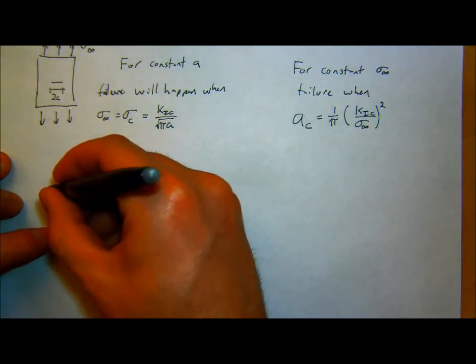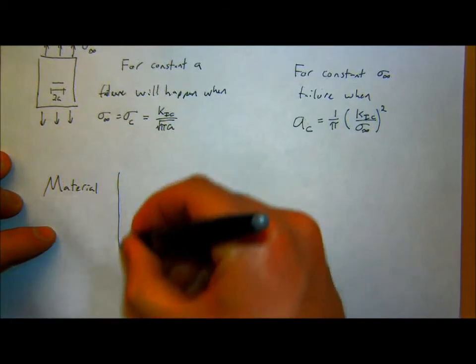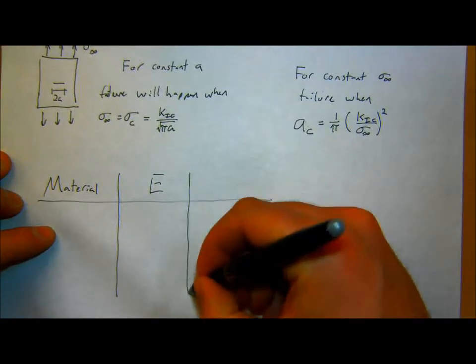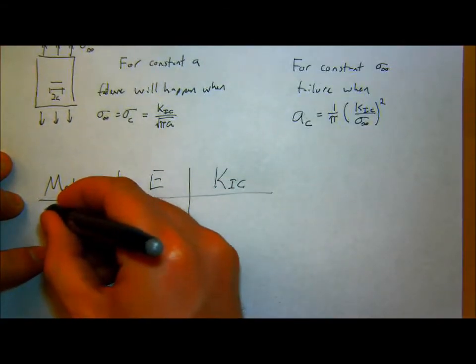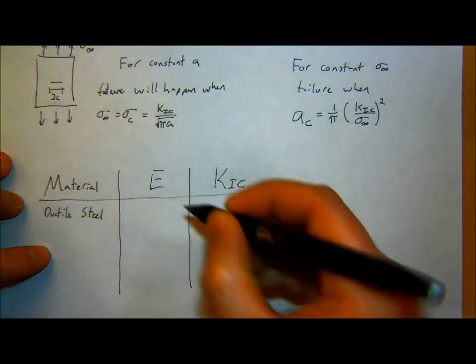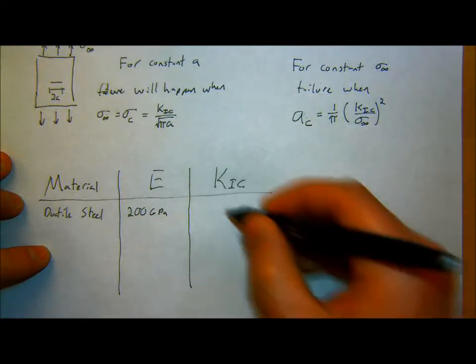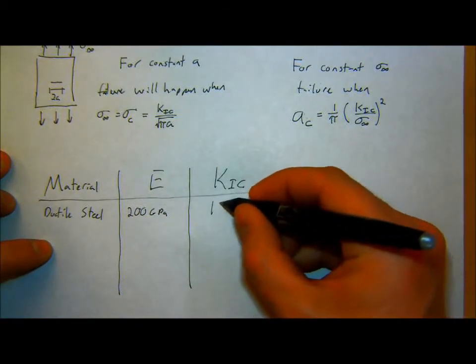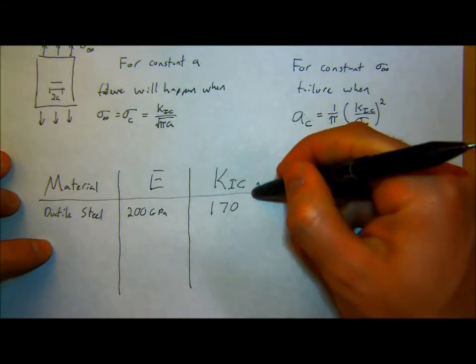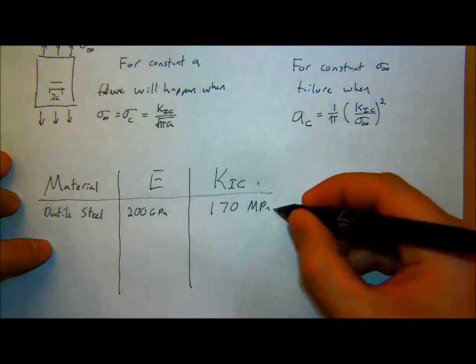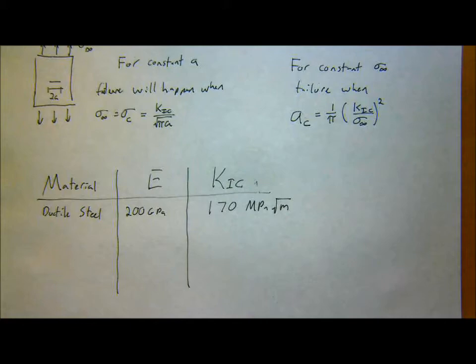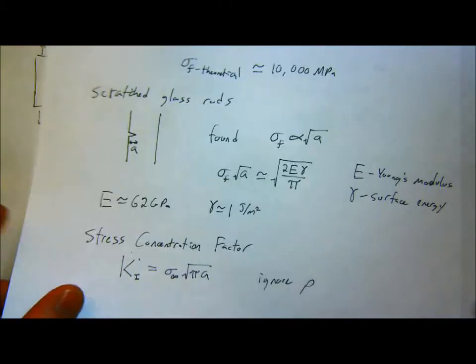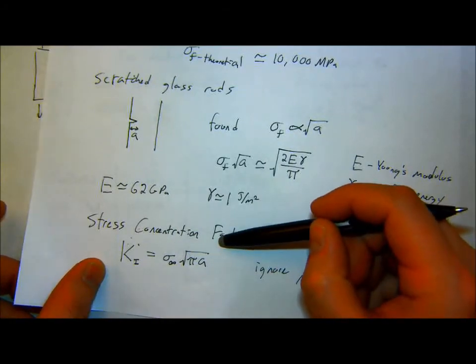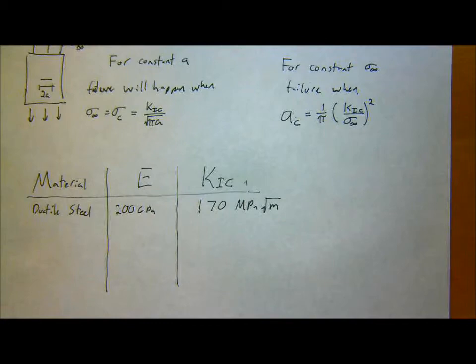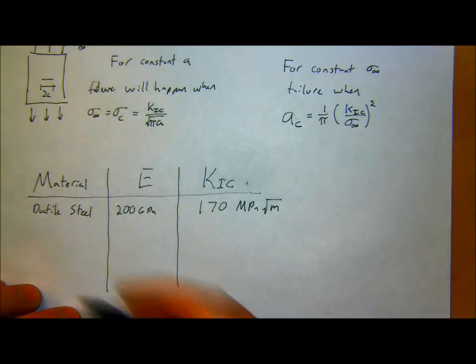If we're looking at something like a ductile steel, our E is on the order of 200 GPa, and our fracture toughness, steels are fairly tough, is on the order of 170. The units for these are generally reported in MPa square root meter, because remember we're defining KIC as our stress times the square root of a, where a is in meters. So it's a weird unit, but this is generally how it's reported. Something like aluminum, say 70-75 aluminum, has something on the order of 70 GPa and has a toughness around 29.